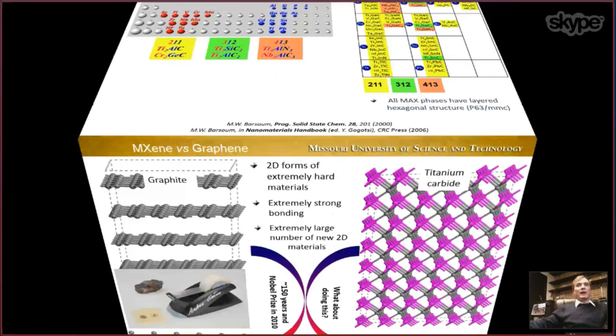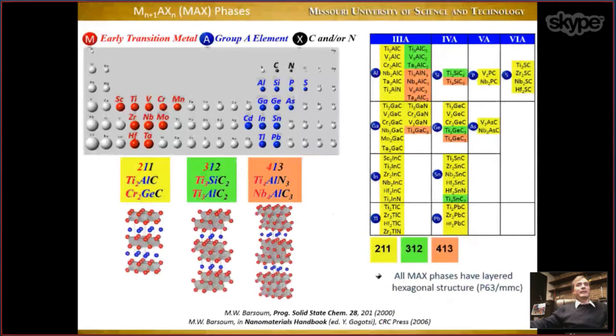Well, of course, Mike is a very smart student, so he did not try to break the bonds in the titanium carbide structure. So the key for this solution was the choice of initial materials. We want to produce 2D transition metal carbides, but we start not with bulk transition metal carbides. Instead, we start with materials which are called MAX phases. What is a MAX phase? Well, a MAX phase is a layered hexagonal material which is formed of blocks of MX with A element layers shown in blue here between these blocks.